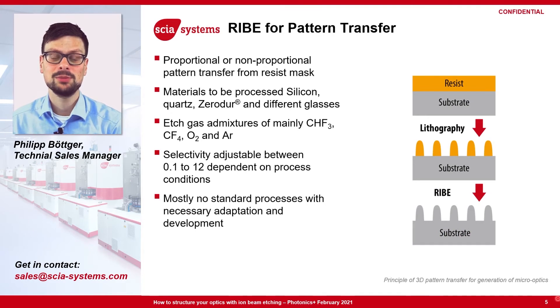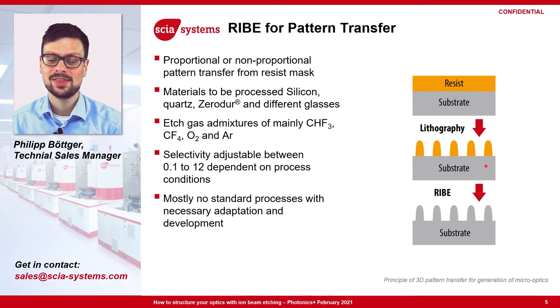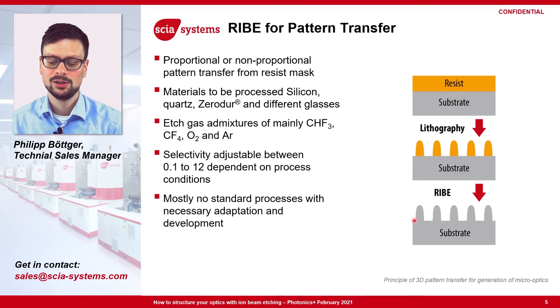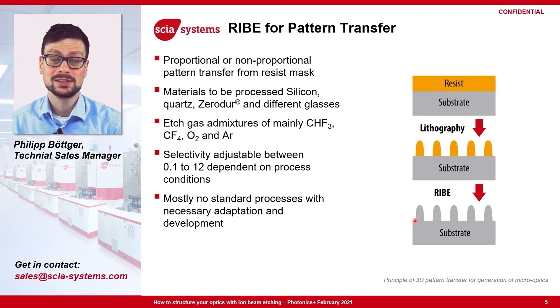A typical application for ion beam etching is pattern transfer. For pattern transfer you need to mask your substrate by either a hard mask or, more commonly, by a photoresist. This photoresist is finely structured by lithography and with ion beam etching we can transfer this pattern into your sample. By choosing appropriate reactive gases it is possible to achieve the same etch rate between resist and substrate, giving you a proportional pattern transfer.